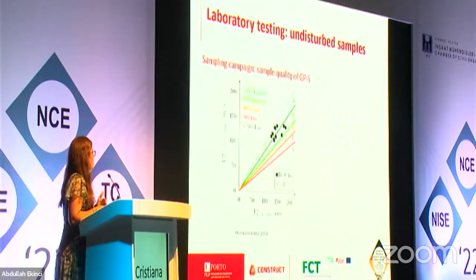So following that, we do the analysis, and we found that the samples are predominantly of excellent or very good quality. But if we look more closely at the open markers, you can see that the bender element test always shows slightly lower results. And this has to do with the lack of confining pressure that's still affecting the measurement of the Bender elements. We get weaker signals and poor resolution, but also the effects of the reconstitution and reestablishment of the in situ stresses.